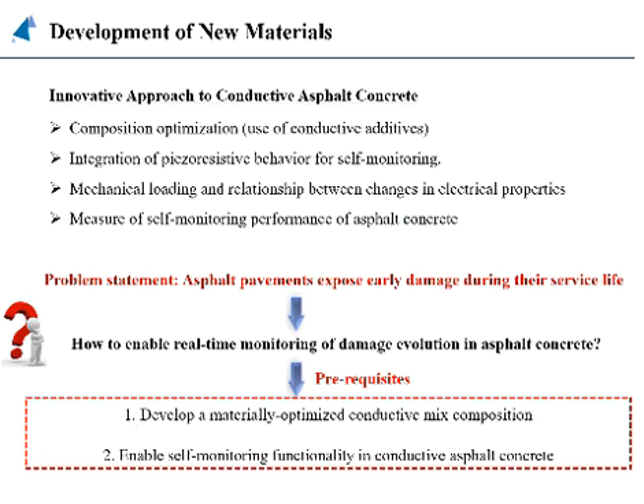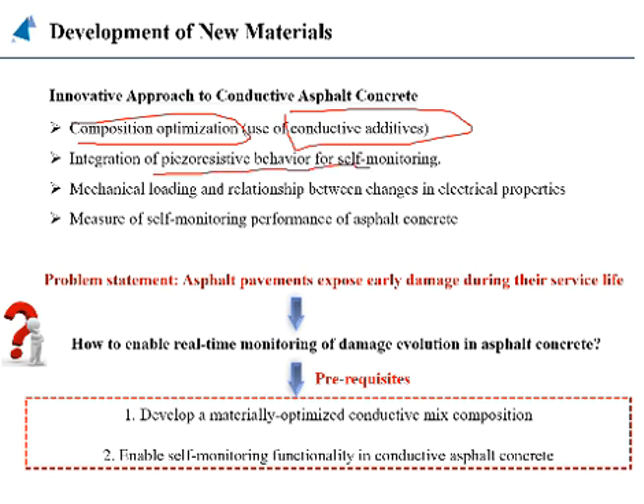Development of new materials, which I did in my PhD research. To avoid these cracks, rutting, and water damages, I modified the composition of the conventional mixtures. I added some type of conductive additives in the asphalt mixer, and I created a piezo-resistive behavior to enable self-monitoring of the material.